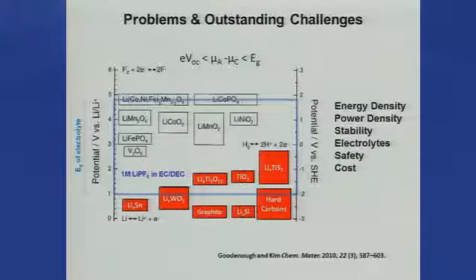And the reason why those are interesting is because they have much higher energy storage densities, the amount of lithium you can store per redox state relative to graphite. Graphite's unique in the fact that it actually forms a passivating layer spontaneously that protects this low potential, and that prohibits things like dendrite growth and the short circuit of the battery.